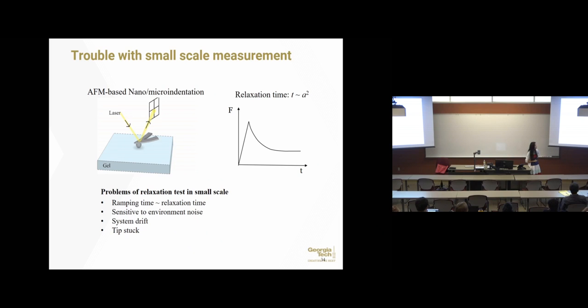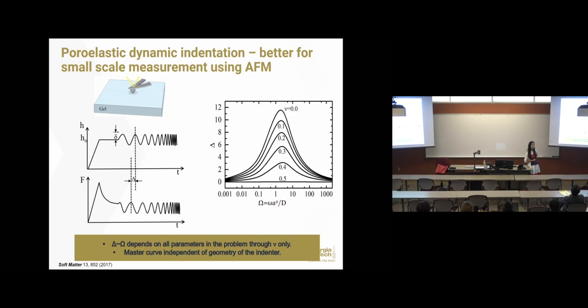But when we apply this relaxation test at small scale, we meet a lot of problems. It's not practical for the following reason. When you reduce the size of indentation, the relaxation time becomes shorter, so the ramping time becomes significant. So you have to ramp it up, load it super fast, and be able to hold there for a longer time, keep the displacement constant for a long time. All these are very challenging at small scale, thermal drifting and everything that matters. So this is not practical, but we found that practically using AFM, we can do very good repetitive measurement in tapping mode, so oscillation mode. That motivates us to revisit this problem theoretically for this dynamic indentation problem.